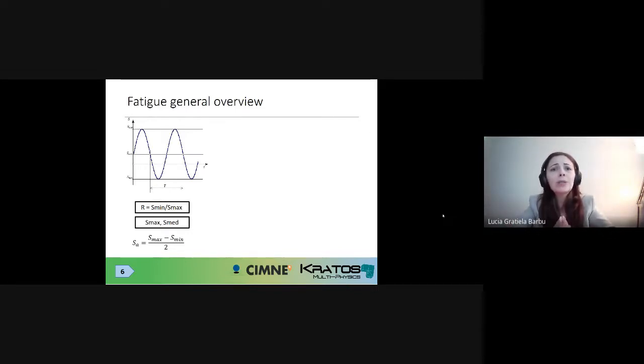Then, what's also important for fatigue formulations, especially in the high cycle fatigue domain, is the maximum level of stress recorded, either at each integration point or in the whole geometry. Also the mean stress, the medium level of stress recorded, because you can have different types of cyclic loading. For instance, completely oscillating, where you have zero mean stress, or you can have tensile mean stress, etc. Also, you can record the amplitude of the cyclic loading and the amplitude of the stress state induced by the cyclic loading. I want to be precise here.